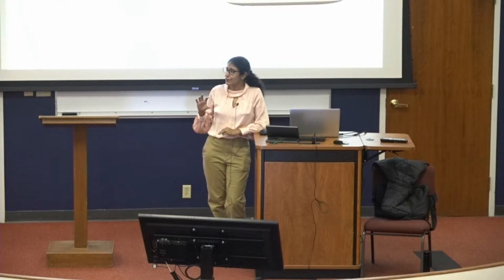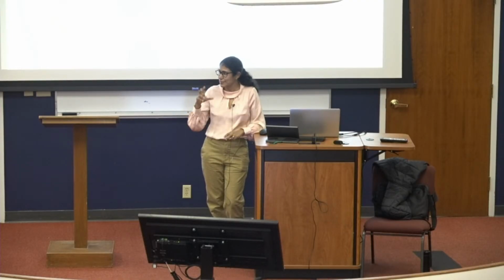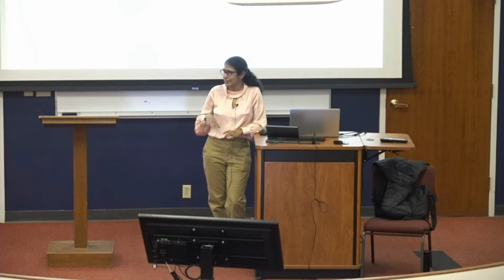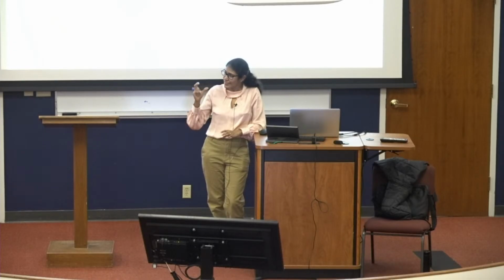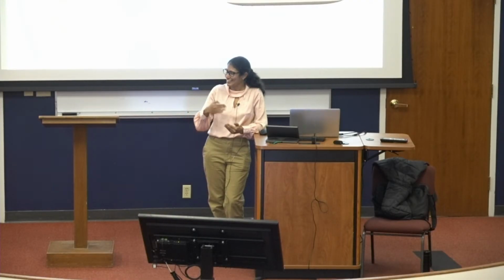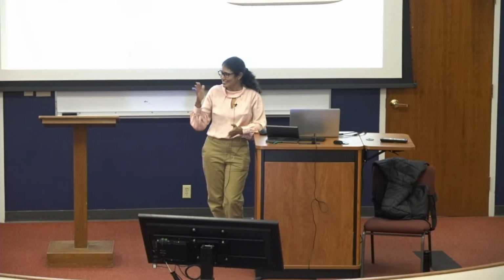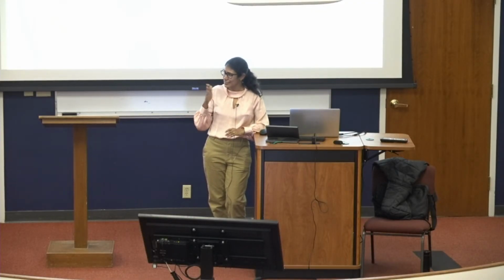That's actually from 5 samples. You take 5 samples of the same size, coated and uncoated. So it's the weight difference that you take. You take the initial weight and the final weight, and then the millimeter per year thickness is based on the calculation. You take the density and surface area, and that's the calculation that gives you the result. That's why it's called the weight loss method. What we measure is the initial weight and the final weight.